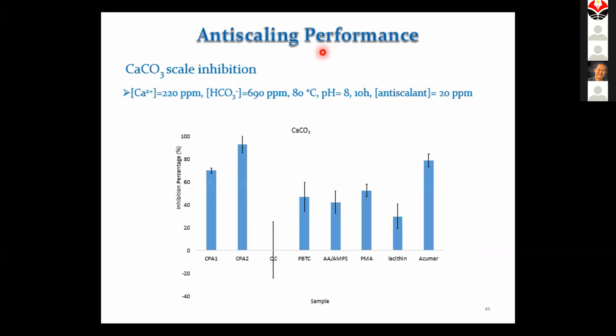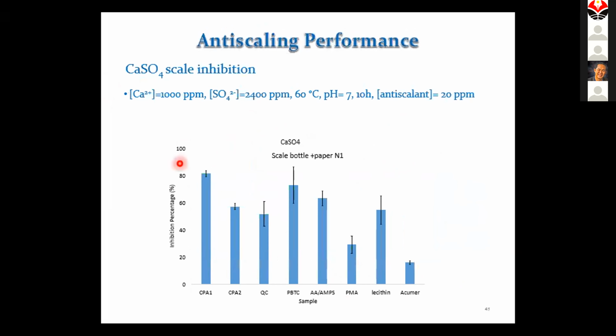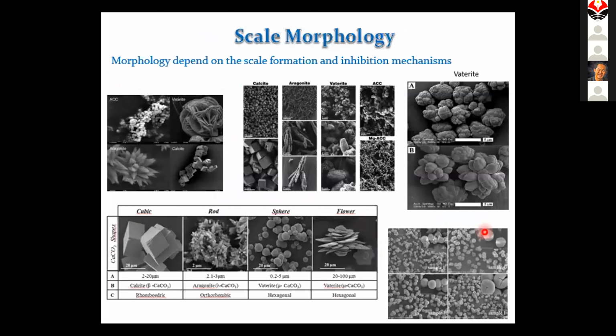This is the performance on anti-scaling. If you look, our CPA, which has both positive and negative charge, works very well, almost 100% anti-scaling performance, compared to existing chemicals in this group like PBTC, AAM, or PMA. Not only calcium carbonate, we also tested calcium sulfate, which also shows very good performance.